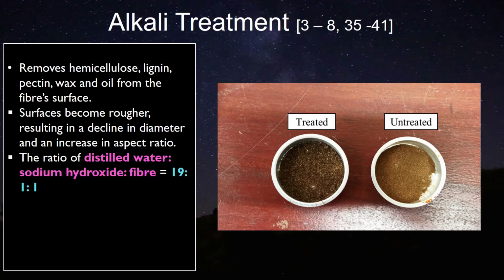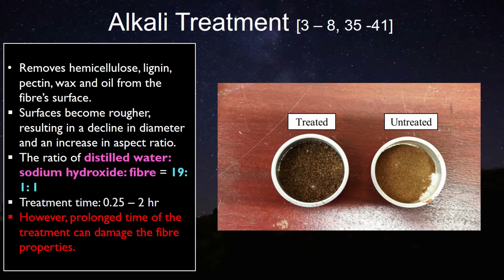After the alkali treatment, you can see the image over there. It's a bit darker, and that's the reason. It actually removes the hemicellulose, lignin, and pectin, and the surface becomes rougher, which is good for further adhesion property. For our research, I used distilled water, sodium hydroxide, and fiber in a ratio of 19:1:1. The treatment time I used was 0.25 hours. The range is 15 minutes to 2 hours.